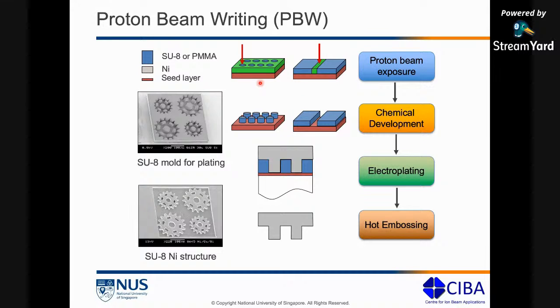So what we do here is we start with a substrate. We spin coat either a negative or a positive resist, and expose the resist to proton beams. So if it's a negative resist, wherever it is exposed, it will solidify. If it's a positive resist, wherever it is exposed, that part will get dissolved. Then we have the chemical development stage. Then this becomes like the master mold at this point.